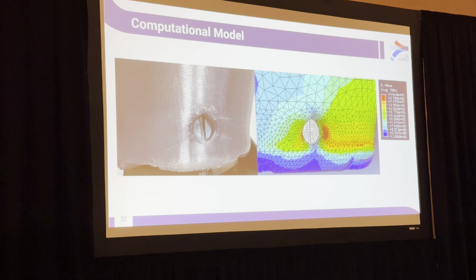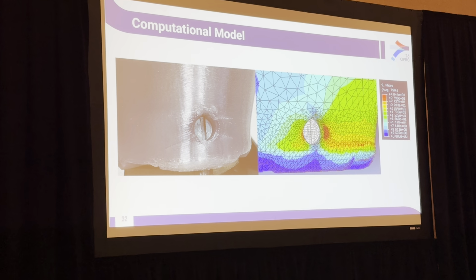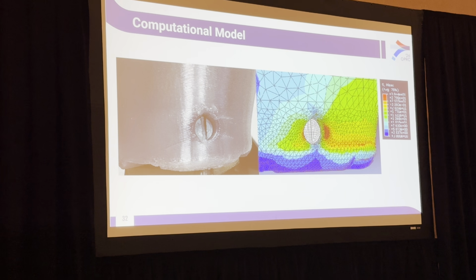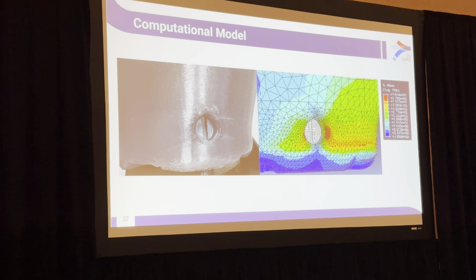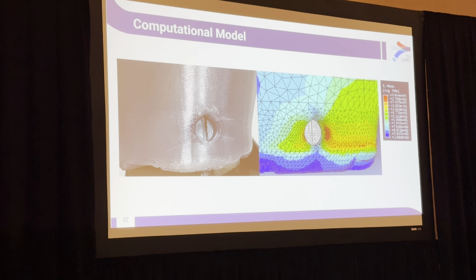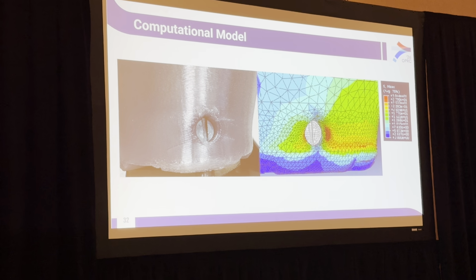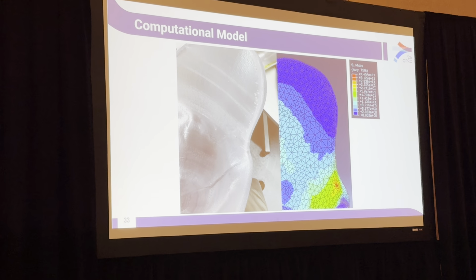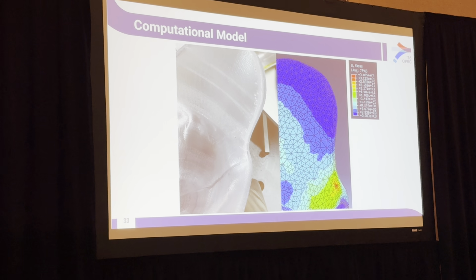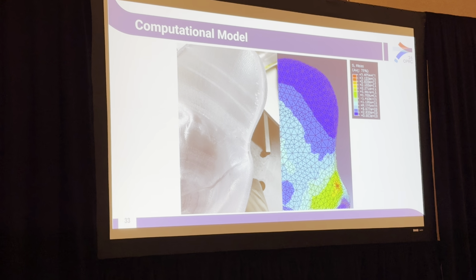So I'll touch a little bit on our computational model. What we did to validate our computational model was compare what our model was predicting as areas of high stress, and therefore more likely for failure, to the actual observed failures within the socket. So you see here the areas in red are areas our model is saying there's a high stress, and you can see the correlation here with that observed fracture. And we see that again in our second location. Testing of the socket is quite time consuming, so to be able to simulate that without having to test sockets is some of the utility of this model.